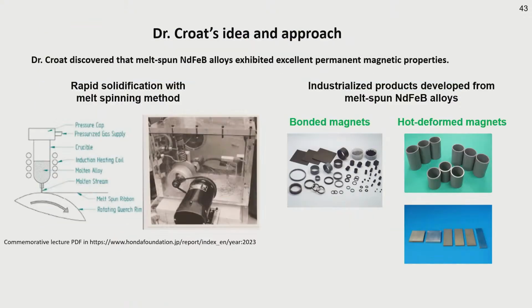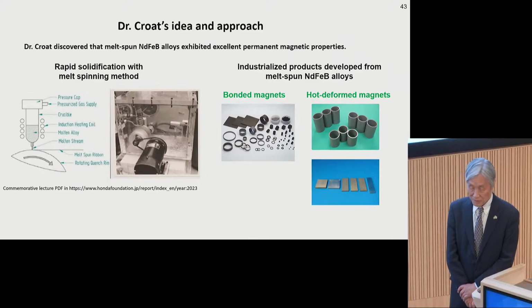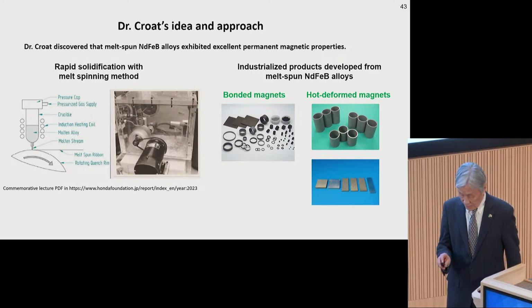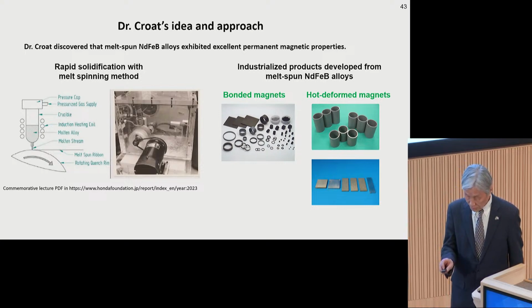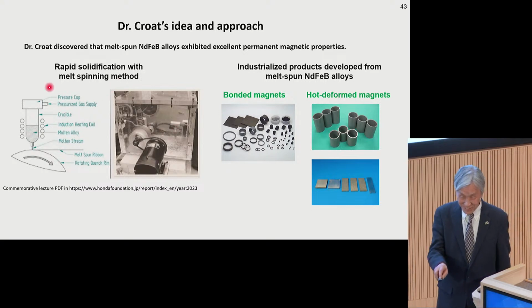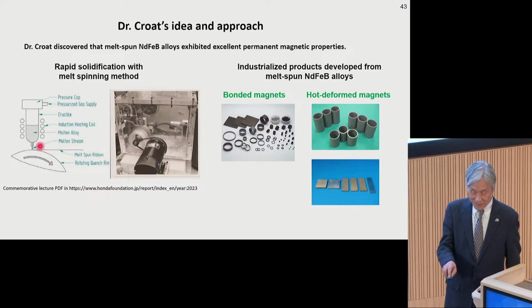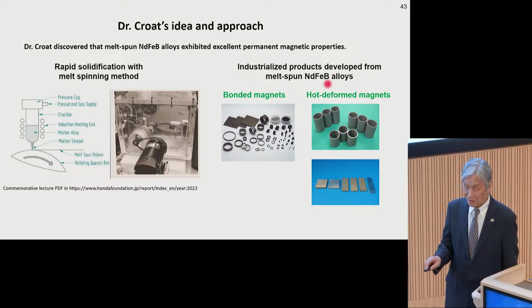Okay, this is the melt spinning method. Dr. Croat's idea and approach. Dr. Croat discovered that melt spun neodymium iron boron alloys exhibited excellent permanent magnet properties. This shows rapid solidification with the melt spinning method. And by this method, the industrialized products developed from melt spun neodymium iron boron alloys, not sintered magnets, but bonded magnets, resin bonded magnets, or hot deformed magnets. By this method, ring magnets and plate-like magnets are produced.